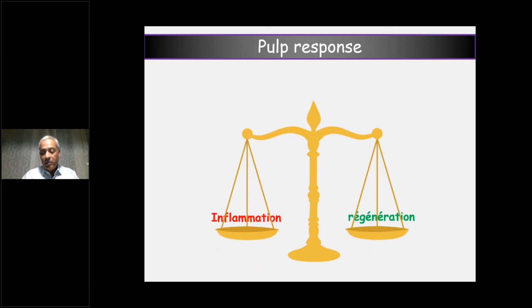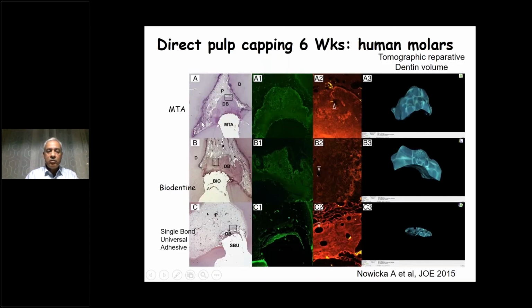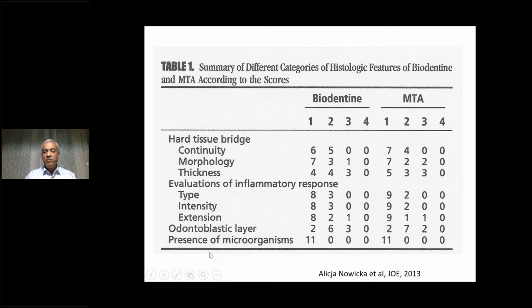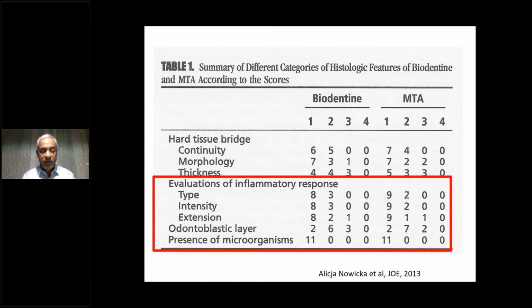If you remember well, whenever you look at any clinical trial with histological evaluation, you see this type of thing. You see dentin bridge formation. This is with MTA and Biodentine, not with a resin-containing material. And then soon after, but many of us forget to look at it, there is the inflammation, and there is the evaluation of inflammation. And this is very important. When you have severe inflammation, you will not have any regeneration. And when you have moderate or mild inflammation, you might have regeneration depending on the material you use.